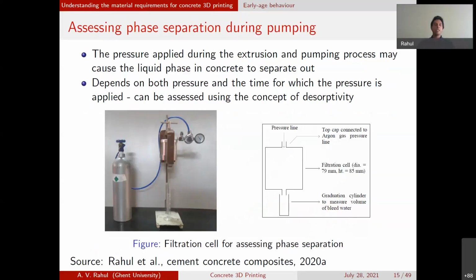Regarding pumping, one more thing that we need to look at, especially if you're using a piston pump, is that sometimes too much phase separation can happen, and this can cause all the liquid to separate out from the concrete, leaving a very thick, unextrudable mass of concrete in the pipe. This is something that can happen sometimes. So it's also important to understand how we can assess this phase separation tendency of the concrete.